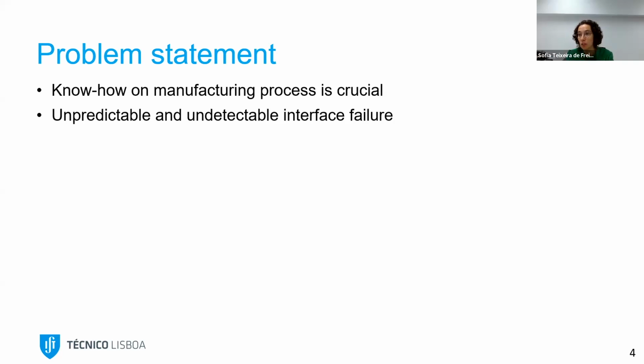With this interface failure the strength is much lower. It is much more susceptible to any type of environmental degradation, so it must be avoided. It must not be in infrastructures, but it's undetectable with our current NDT techniques, non-destructive techniques, such as ultrasonic C-scans. They cannot detect this type of bonded joint. So this is a huge limitation for applying bonded joints in full-scale primary structures.